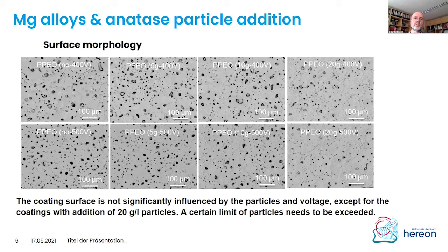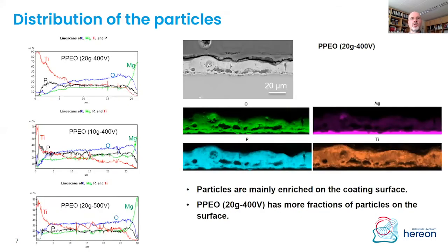And if you look at the surface morphology, you see that up to a certain limit, which is about 20 grams per liter of the anatase particles added to the electrolyte, the surface morphology looks somewhat similar for all. But at 20 grams, it basically starts to change. We see that the particles start to fill the open pores, and we see effects of sealing. So what is actually going on?